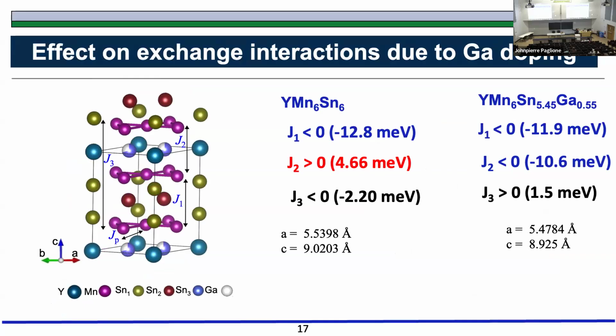And now what this means is that this is a ferromagnetic interaction, this is also a ferromagnetic interaction, they are comparable. So they are hard to twist by the third interaction. So they prefer to be parallel with one another in every plane. And then we get a nice ferromagnet, that's ferromagnetic in the plane.